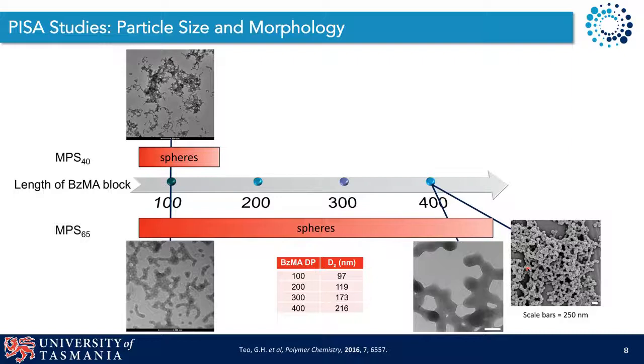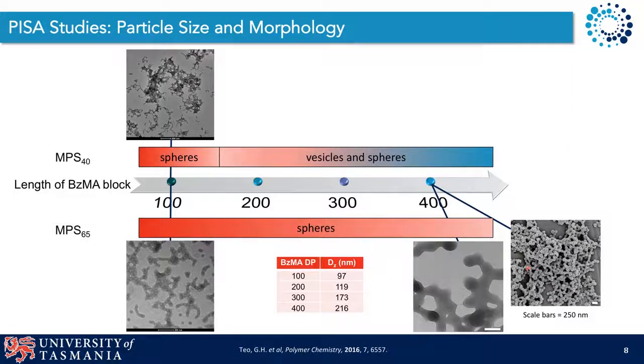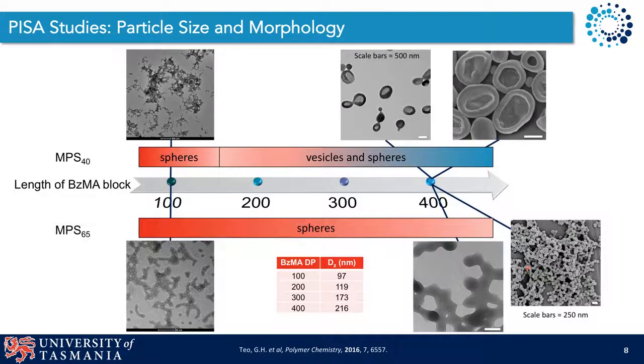Dropping the length of our stabiliser block from 65 to 40 did indeed yield vesicles from approximately a DP of 150 onwards of the benzyl methacrylate block. And we can see by TEM quite a clear demonstration of vesicles that collapsed on the electron microscope grid, of relatively uniform size and thickness of the wall.